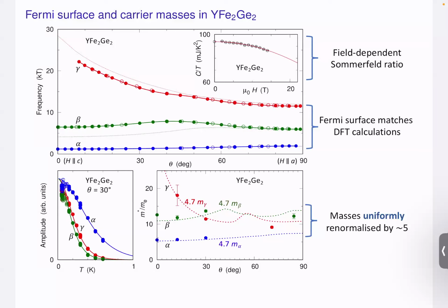Looking at the mass measured on these three Fermi surface pockets by doing measurements at different temperatures, you can find that the mass determined at different angles, these are the dots, tracks very well the DFT computational results if you multiply the computational results by a factor of 5. Okay, so the computation gets it wrong, but it gets it wrong by the same factor every time, every direction, every sheet that we could measure. So it's a uniform mass renormalization.